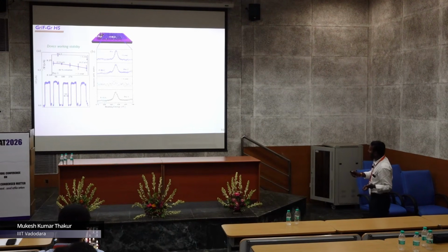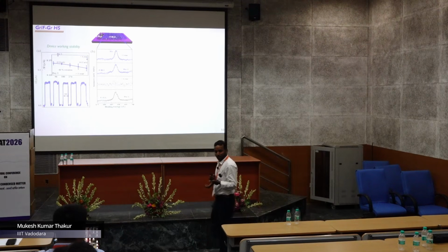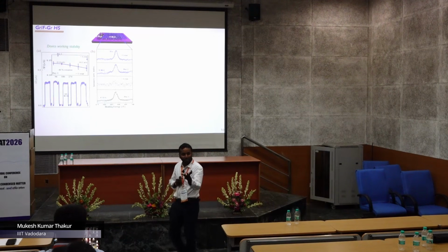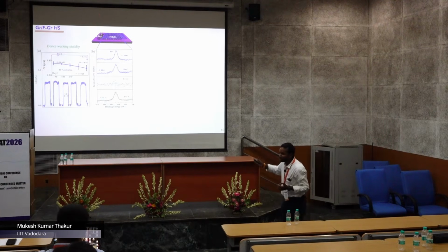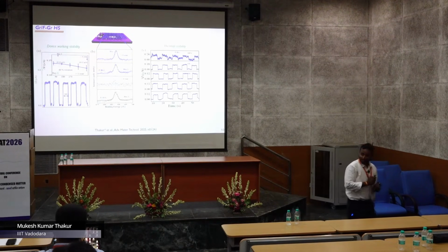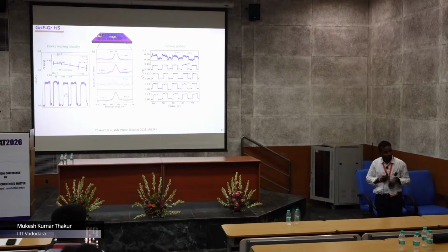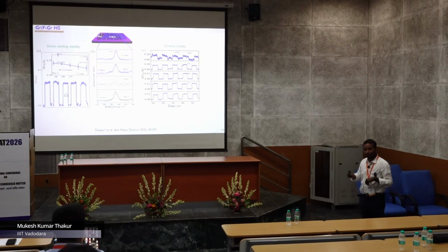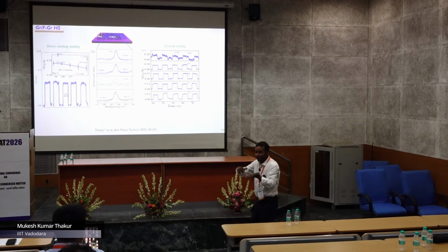Another thing, we also checked the stability of this sample by Raman spectroscopy. When we heat, up to what temperature can this fluorine bind with the top layer of graphene? And here is our photo response with temperature. What we observe is that up to 200 degrees Celsius, this device was quite stable. Why? Due to this top layer, because it provides some kind of capping and also holds the fluorine, and that's what we need, right?